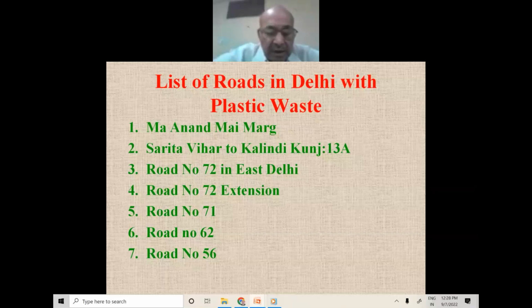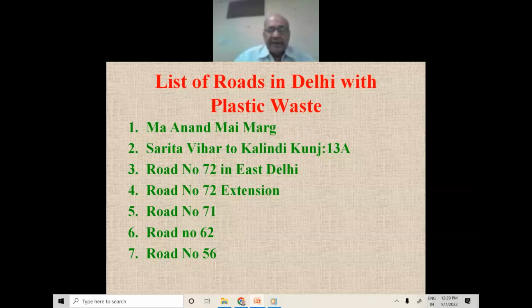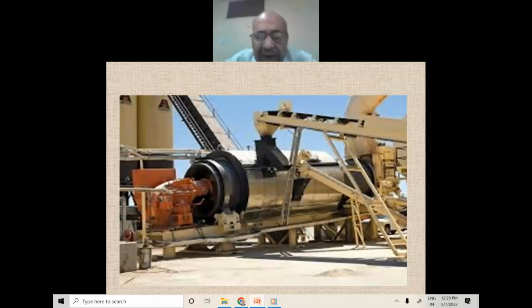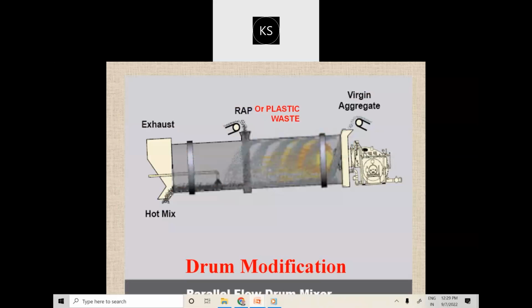So after 20,000 passes, we can say the rut depth in the plastic waste modified mix is only 6 millimeter, which is 8 millimeter in case of the unmodified mix. So we can observe 25% less rut depth in case of the plastic waste modified mix as compared to the normal bitumen mix. So this is all about how we can do the performance studies and the results of a typical case of the performance study on unmodified as well as the modified plastic waste mix.